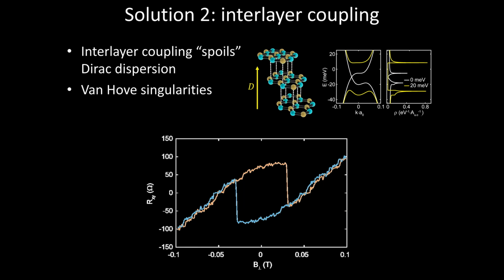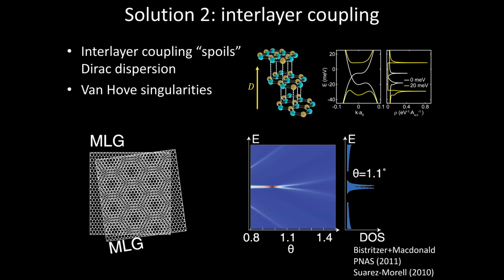And in fact, in almost every type of graphene at this point, you can find a regime of parameter space where you're near one of these Van Hove singularities, which are just a generic feature of interlayer coupling and the C3 symmetry of this lattice. You can find regimes where you have some kind of magnetic state. So here's rhombohedral graphene. You sweep a magnetic field and just measure the Hall resistance, and you see that there's hysteretic behavior that's associated with polarization into one or the other valley and the formation of a spontaneous orbital moment.